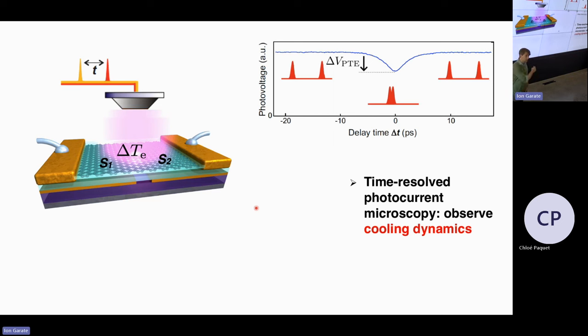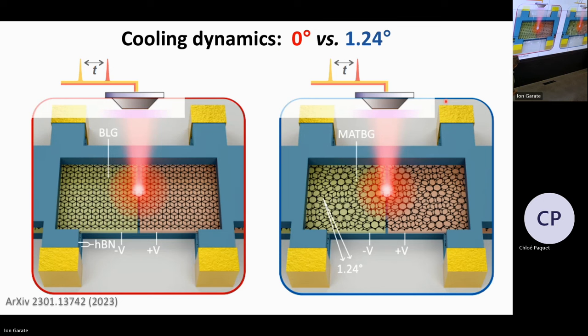So what we're going to do is take our graphene photodetector type sample. We have these two split gates. We have the PN junction where we generate this photovoltage. Now, in this case, of course, we don't just have a graphene channel, but a channel consisting of twisted bilayer graphene. Then we're going to do these dynamics measurements and see how fast these systems cool. We're going to do that comparing two different samples. We also have a third one, but I don't show it here, but it looks very similar to the one on the right. So here we have normal Bernal stacked, non-twisted bilayer graphene, so 0 degree angle.